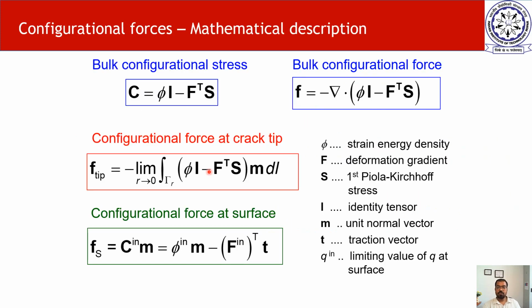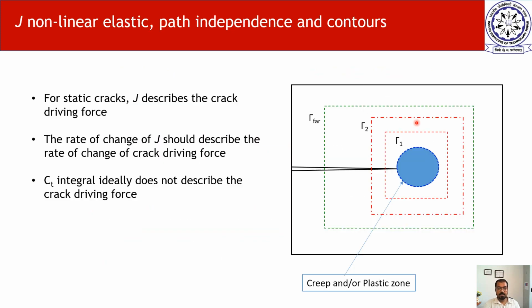We calculate configurational force using these formulas in finite element analysis by post-processing the parameter values at the integration points, and the main concept is here. So C is the configurational stress. It is also the Eshelby energy momentum tensor, and the divergence of that gives me the configurational force term. So divergence basically means the inwardness or outwardness of whatever parameter's divergence is being calculated. So when this value is 0, it would mean that there is no inwardness or outwardness of the energy which is coming in and going out. And if this is a non-zero value, then there is a net configurational force at that material point. So that's how we calculate it.